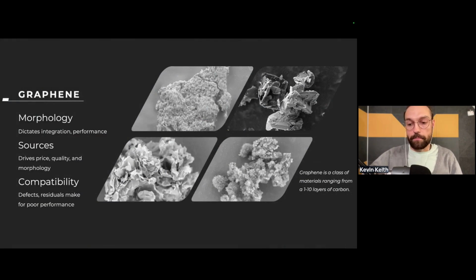drives it. I'm very sure that most everybody here is very aware of what graphene is, but setting the tone, graphene is a class of materials ranging from 1 to 10 layers of carbon allotropes. These 4 pictures here are different forms of graphene, whether it's more micron size, nano size, different layer counts, they're all classified as graphene. Within that structure, you have different morphologies, which dictates integration and performance values, as well as the sources. The source of the graphene drives price, quality, and morphology. And we'll get a little bit more into that later, as well as the compatibility of the graphenes. So the defect count, the residuals, they can make for poor performance if you don't tailor it just right.